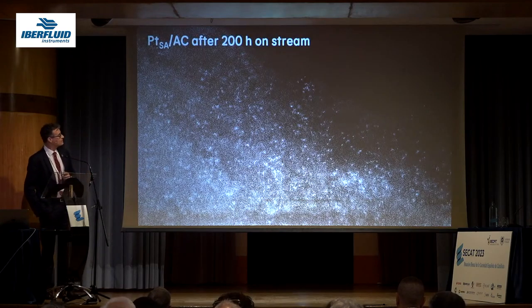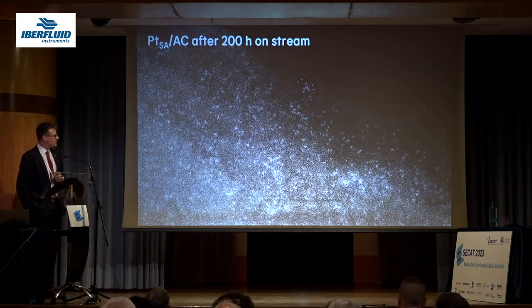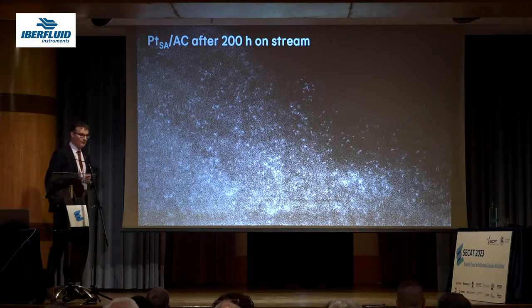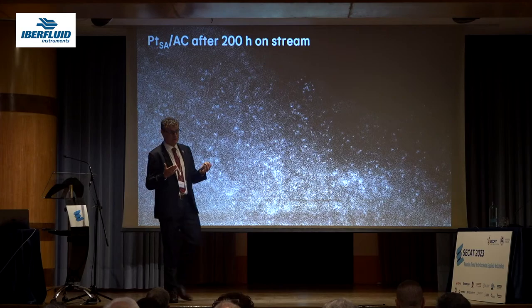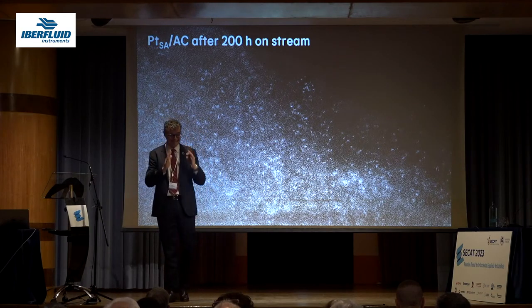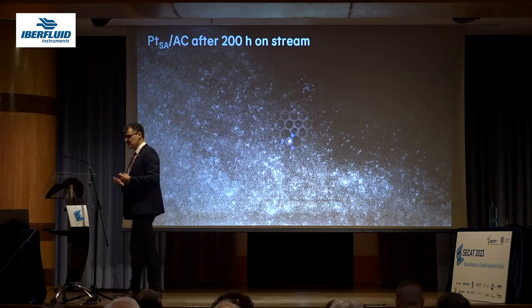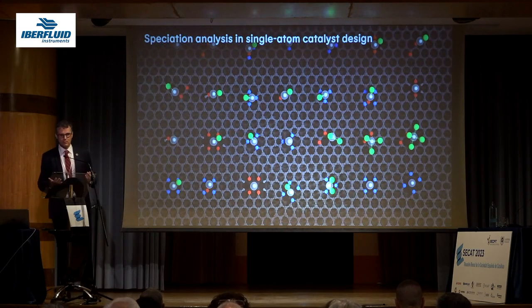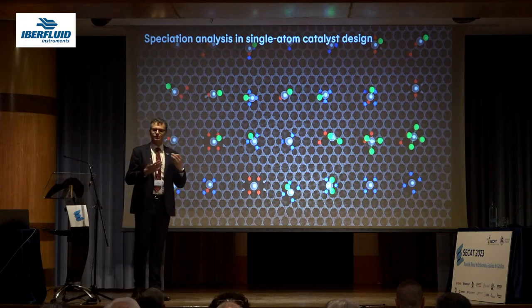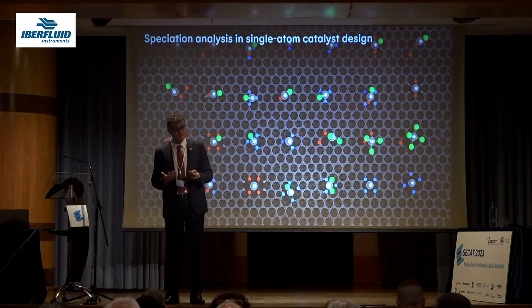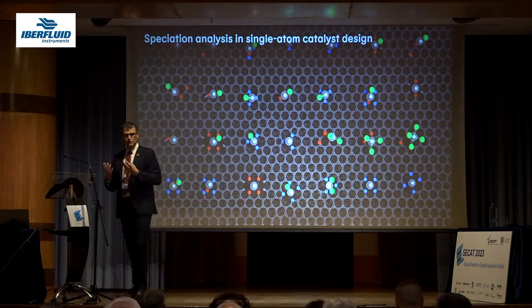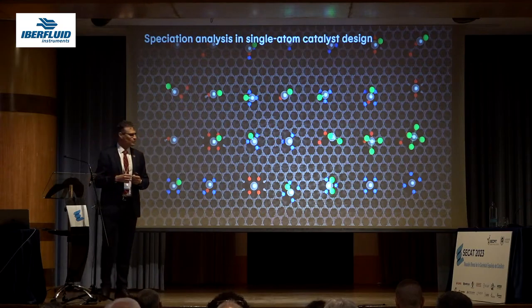And so this is an image of a single atom of platinum after 200 hours on stream, where you see the dots are single atoms. And very often you say, okay, well, these are platinum single atoms, the story is over. No, the story is not over. The story has just started. Because each of these dots could be a very different species. Where do you have the platinum? Is it attached to oxygen on the carbon? In what geometry, in what cavity, or to the nitrogen heteroatom? What kind of degree of chlorination does it have in steady state conditions? And for that, you need operando techniques. Because you cannot just do ex situ characterization of used materials and try to determine the dynamics of this single atom under reaction conditions.